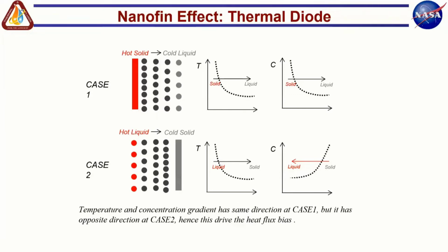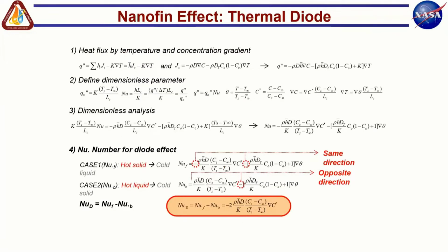direction. On the other hand, if you have a hot liquid and a cold solid, now your temperature gradient and concentration gradient are actually fighting each other. And so if you do the math, if you calculate the Nusselt number based on the Soret effect and the Dufour effect, and if you take Nu sub F as the heat transfer in the forward direction, which is hot solid to a cold liquid, your temperature gradient and your concentration gradient are actually helping each other. On the other hand, if you have a Nusselt number backwards, then they are actually competing with each other.